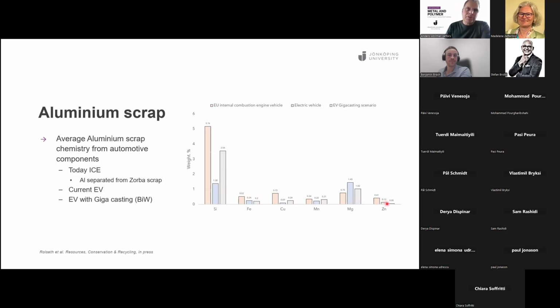Now, the thing that happens when you do the mega casting is, of course, that the mega casting cannot utilize these low values of silicon to have an average content of the car. If you add on the rear floors, you end up with about 3.5% silicon in the scrap that comes back.